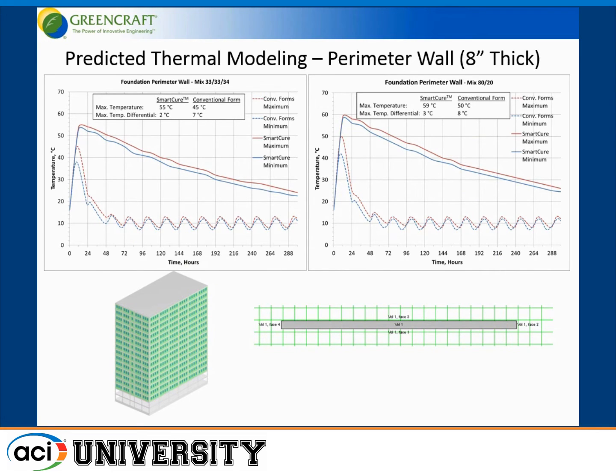Then we move to the foundation wall and the rest of the wall, and the notion here is that that low carbon mix, the SmartCure concrete, produces better physical and chemical properties. We can take that mix now vertical and use it in all these elements where before you couldn't. And here we model side by side the 1/3, 1/3, 1/3 mix and the 80-20 mix. The 80-20 mix would be a mix that you would use, pretty much, in a vertical application like that.